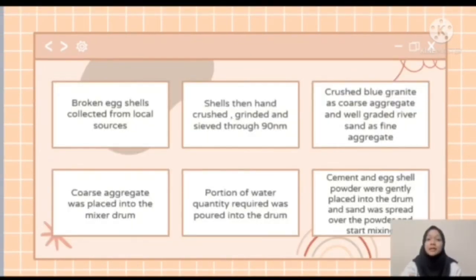For the methodology part, it starts with broken eggshell collected from local sources, and the shells were cleaned with regular water and air dried for about 5 days at temperatures ranging from 25 to 30 degrees. Secondly, the shells were hand crushed, ground and sieved through 90 µm. The material that passed through the 90 µm sieve was used to replace the cement, while the material left behind was discarded. Next, crushed blue granite was used as coarse aggregate and well-graded river sand as fine aggregate.